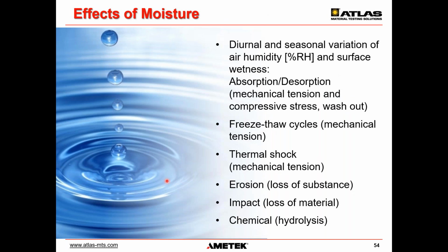And there are other effects of moisture like thermal shock, which is relevant. There are erosion effects, impact effects, and there are also degradation reactions, especially for hydrophilic polymers, which can be caused only by water, by humidity, hydrolysis effects, and so on.